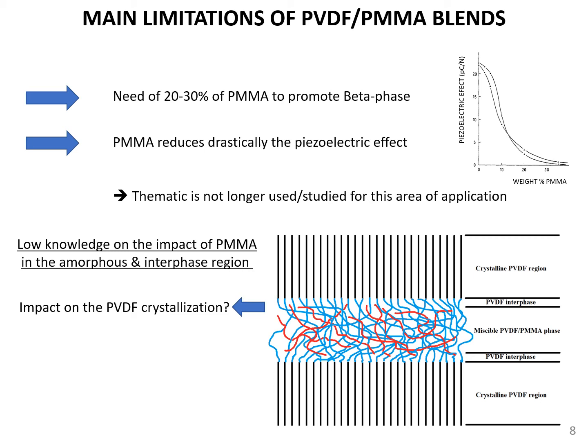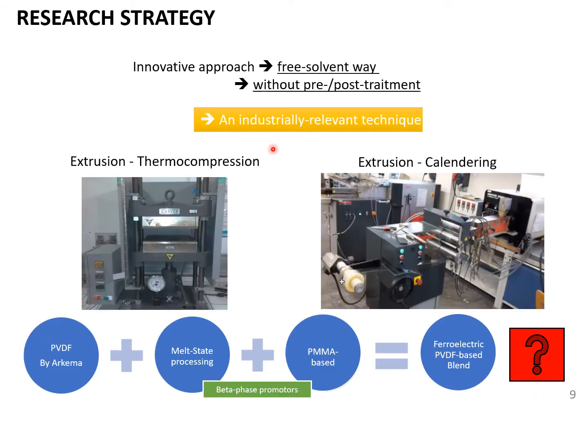Therefore, it was very important in the investigation we carried out in the joint PhD to understand the crystallization and also the coupling that you can have when you add PMMA inside this type of system. So we have an innovative approach based on solvent-free processing to understand the influence of PMMA on PVDF crystallization. The motivation was based on extrusion technology, which is an industrially relevant technique, and we carried out the compounding with PVDF and PMMA by melt processing in order to investigate the beta phase.